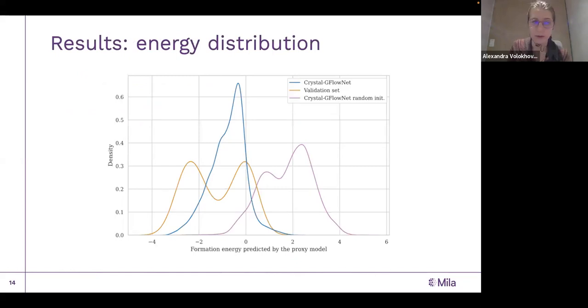And the results which we have, we analyzed in two ways. One was the energy distribution of the sampled structures, and then we also tried to analyze their diversity. So let's start with the energy. Here is the plot which represents the distribution of the formation energy predicted by the proxy model for different sets. The blue one is the samples sampled from the trained model. The orange one is the validation set, and the pink one is the set sampled from the randomly initialized model.